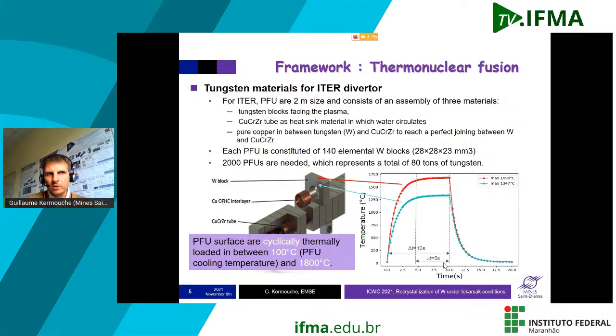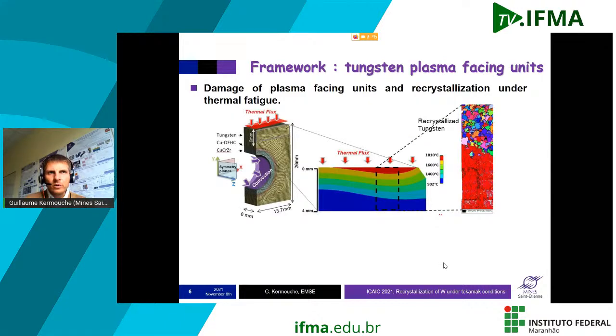When there is a cyclic solicitation, clearly there is some damage that can happen in the material, some thermal damage. So clearly, designing plasma facing units deals with fatigue damage. Let's now focus on what happens in a single monoblock. You can see here a finite element model, a classical model, with heat flux. Clearly, you can see the temperature gradient in the material, between 1,800 and here 1,000 degrees Celsius. If you look at the microstructure of the material after a given number of cycles, maybe after 10 cycles, you will see that the material here is a bit different from the material in the depths.